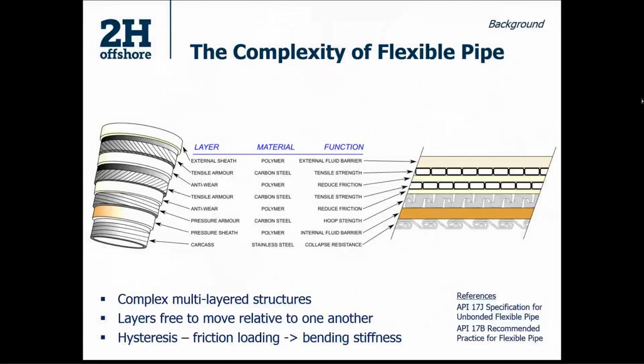With the wave loading cycle, the bending and unbending of the pipe, the stiffness behavior will change. So it goes from what we would expect to be a linear behavior to a non-linear behavior, and that has a big impact on predicting the remaining life, because we're effectively going to be calculating fatigue, and the bending stiffness has an impact on that. So two of the references that I'll use quite a bit through my presentation, through the webinar, are the API foundation documents, the specification for unbonded flexible pipe, and the recommended practice for flexible pipe.